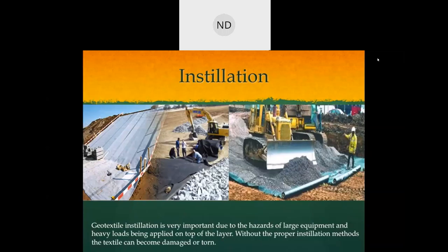The geotextile is put into place by rolling it out on the subgrade. In order to hold the fabric in place until the top aggregate is installed, it is acceptable to use either pins or weights. The aggregate should be back dumped from a lower height to prevent any tears in the textile. These heavy units are often dumped onto the geotextile filter layer from a certain height, which induces high dynamic impact onto the material. This would result in the loss of mechanical strength, hydraulic efficiency, or severe puncturing of the material.